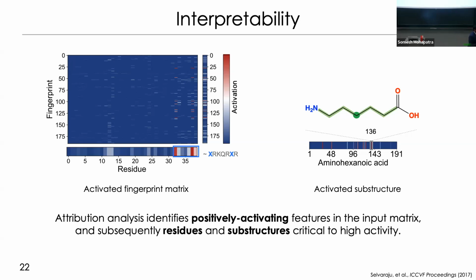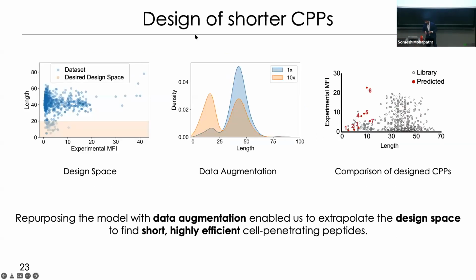But looking at the data set, it was almost impossible to do so, because our data set had a mean length of around 42 amino acids, and our desired design space was less than 20 amino acids, which did not have peptides that were as active as we would want them to be. So we used a trick. We used a trick referred to as data augmentation.